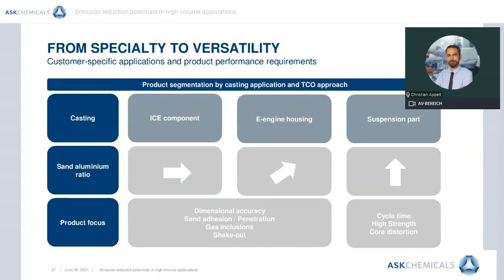ICE components, for example cylinder heads and crankcases, show a very balanced sand-aluminum ratio, while the ratio value is already increased for e-engine housings. Both casting types need in general binder systems that ensure high dimensional accuracy, as well as sand cores with a low gas potential and very good shakeout performance of the cores, as both components use filigree water jacket geometries. In comparison, suspension part castings are produced using voluminous sand cores. Thus, the sand-aluminum ratio is higher, and the main product focus changes to cycle time, strength, and core distortion, all parameters of the core production process itself. The following 2 slides will be used to demonstrate the effectiveness of this approach.